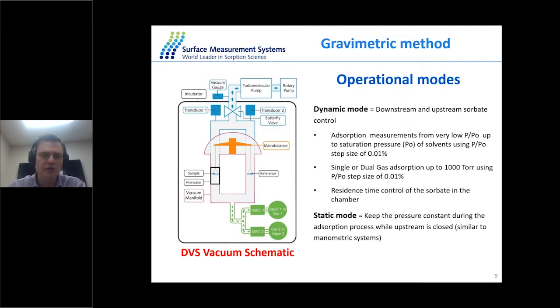So dynamic mode is basically that we flow a small amount of vapors over the sample while we keep the total pressure constant. So we set the flow rate, let's say on MFC1 to 5 ccm. We set the partial pressure of water, let's say 10% P over P naught. So what it means, we measure absolute pressure. So we need to know the saturation pressure of water at 25 degrees, which is 23.8 torr. So if you want 10%, it means 2.38 torr absolute pressure. So this valve closes, we fill up the chamber with water vapor.